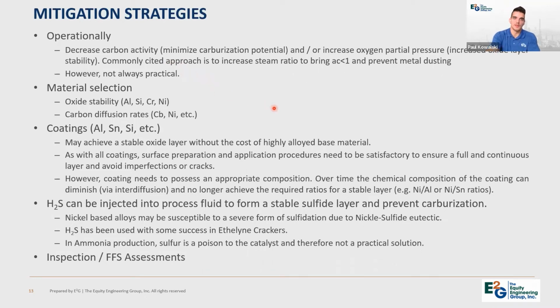So then another common mitigation strategy may be a material upgrade. Install a material with better resistance, and maybe we won't observe the severe damage. So as mentioned earlier, the resistance of a material to metal dusting is directly correlated to the stability of that oxide layer. So we could choose or install materials with various elements. We mentioned that aluminum and silicon have some of the more stable oxide layers, relatively speaking. So we can choose a material that is higher in these two, and perhaps the oxide layer will stay intact and metal dusting will not occur.